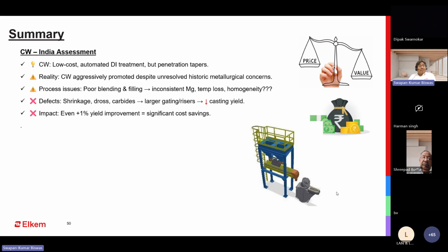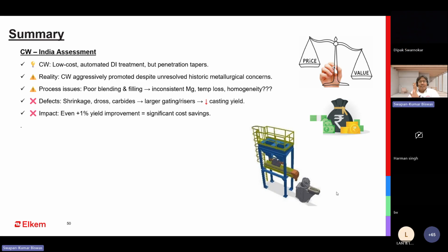So in short, summarizing the cored wire treatment, there are defects in shrinkage, dross and carbide. These are the most common cases we observe. Carbide also. And there is a lower casting yield, because of the increase in riser and runner size, there is a loss in the overall casting yield. And from the metallurgical point of view, there is no consistency. Always there will be variation from heat to heat, and your magnesium recovery is on the lower side. This is the overall summary on the cored wire treatment.